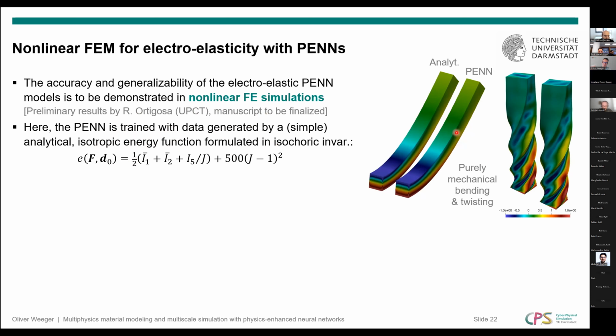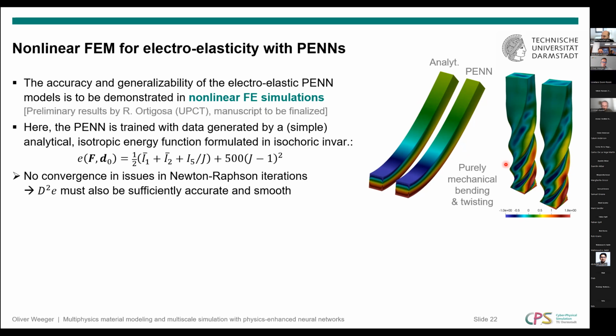One case where you have a beam that is bending, and the other case, a very strong twisting of a column. And if you look at just the comparison of the deformations and of the stresses that are visualized here in terms of the colors, you see that they are very, very similar. So this means basically that we have no convergence issues, and we get accurate results here for these mechanical cases. So these are all highly nonlinear computations. So we use a Newton-Raphson method to solve the nonlinear finite element problem. And in order for that, we must get the second derivative. We must get the elasticity tensor. And this seems to also be accurate, because otherwise we wouldn't get these results.